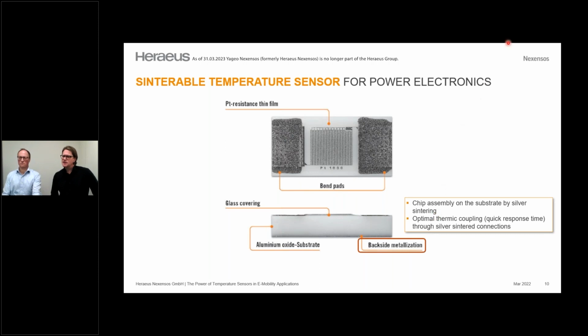On the back side, we have a silver layer, which is ready for silver sintering. This silver layer is made for an optimal thermal coupling, and this leads in the end to a very, very good response time, which helps us to react very fast to protect the power dies.